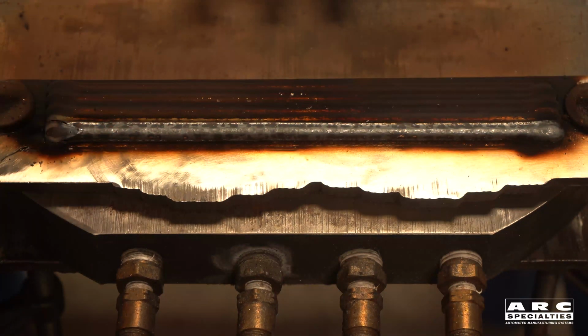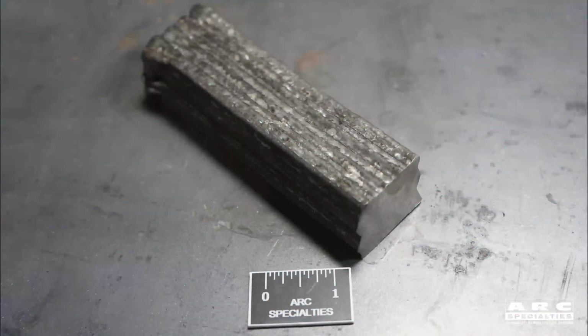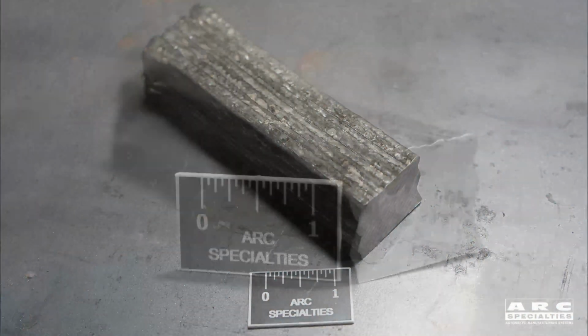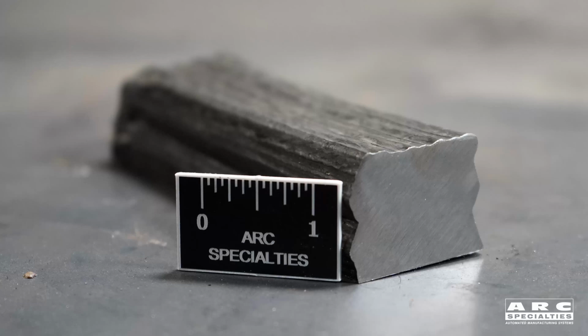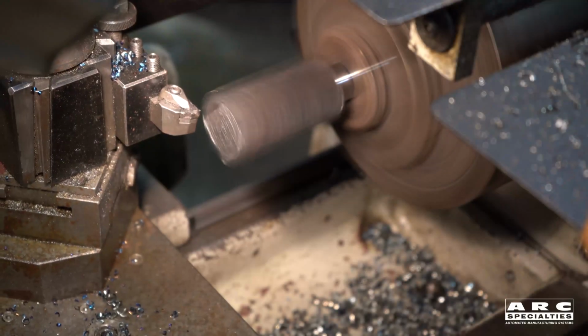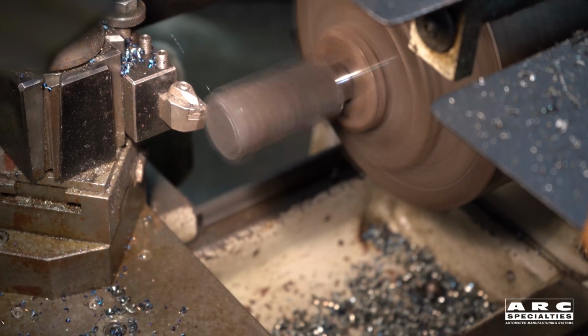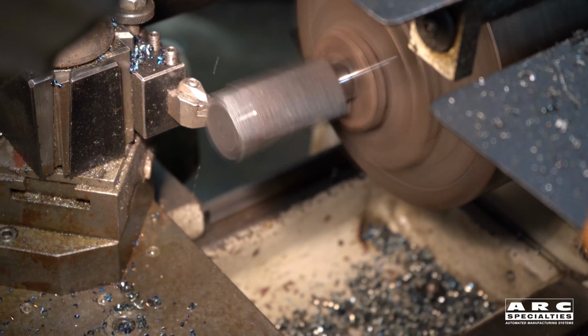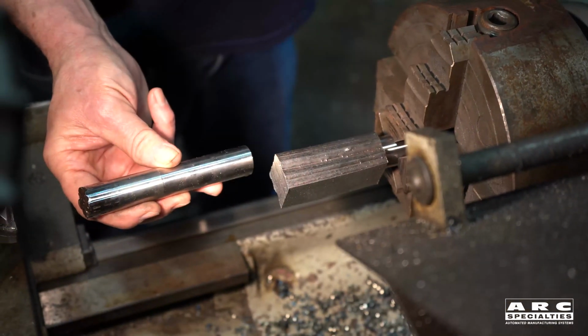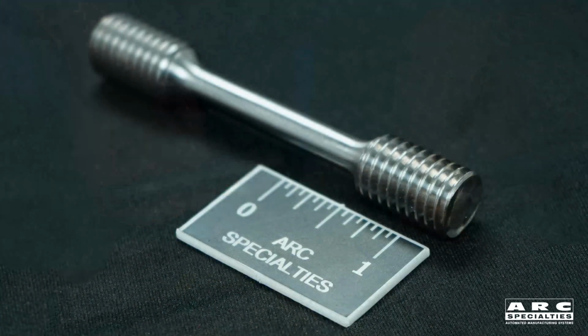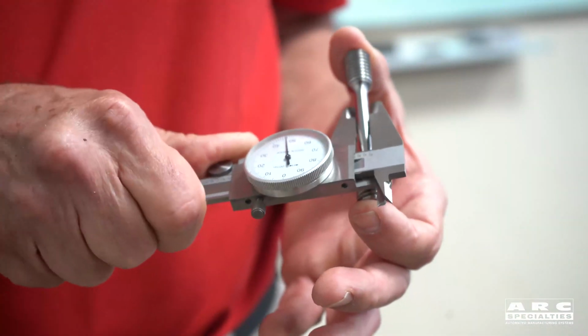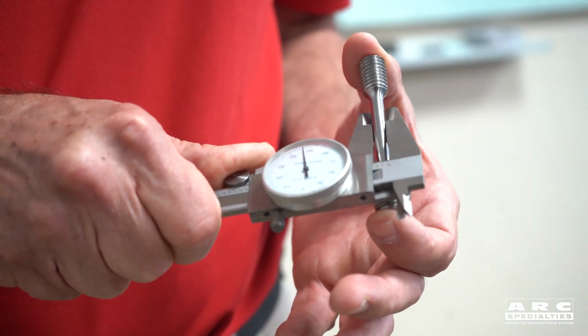After we finish making these welds, you can see here on the time-lapse photography, we make a big block. Next thing we do is we go to the machine shop and we're going to turn this into a 0.250 diameter tensile specimen. Henry's turning the square into a round part, and then we'll actually machine the tensile specimen from there. The cross section of this tensile is only 0.25 inches, so relatively small, and now we'll be able to test that sample to determine the unit stress capacity of it.